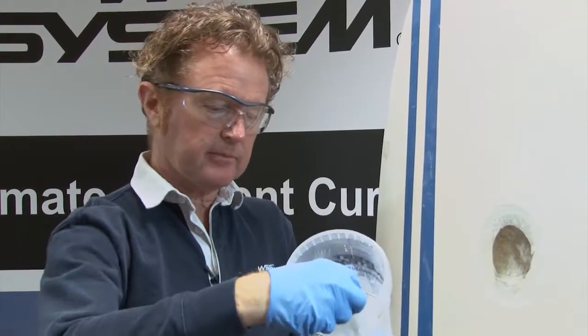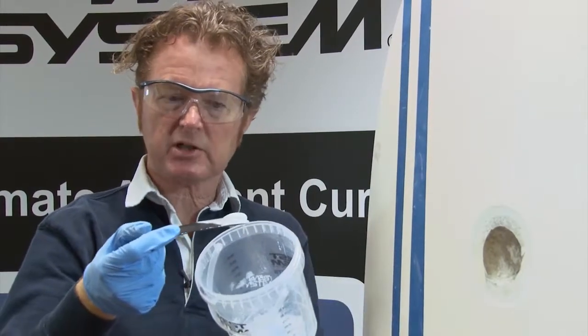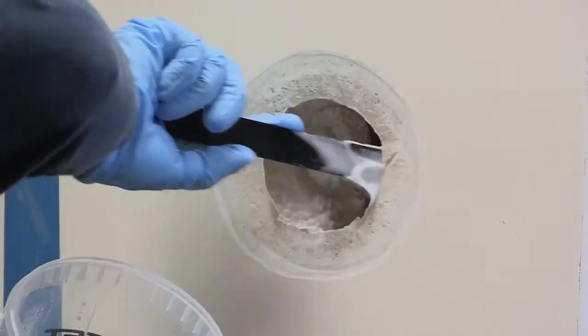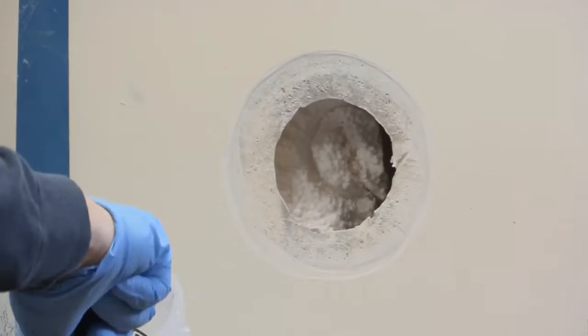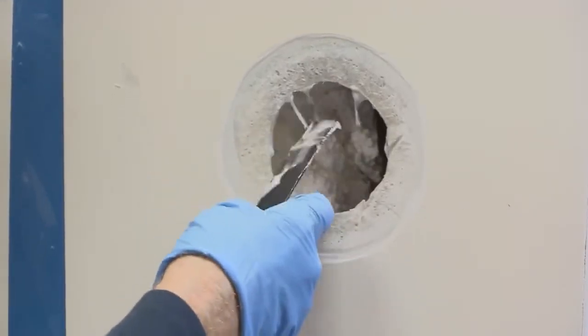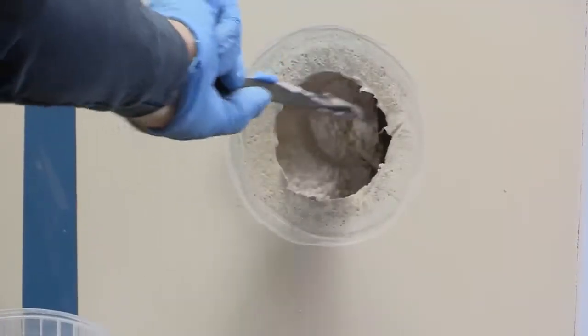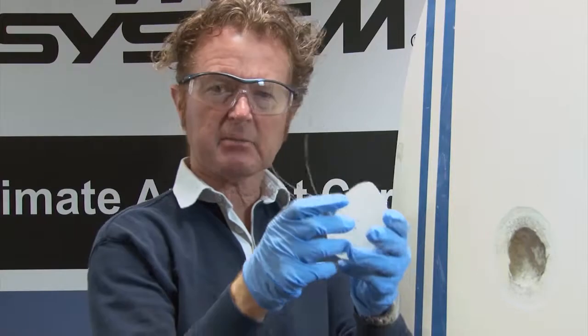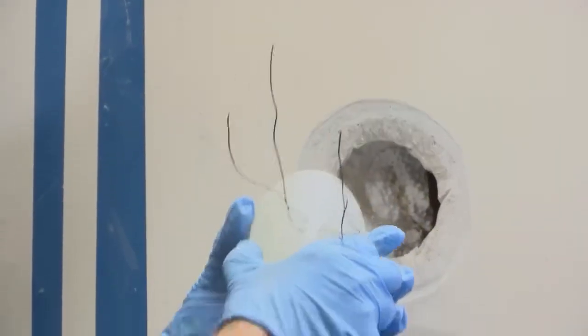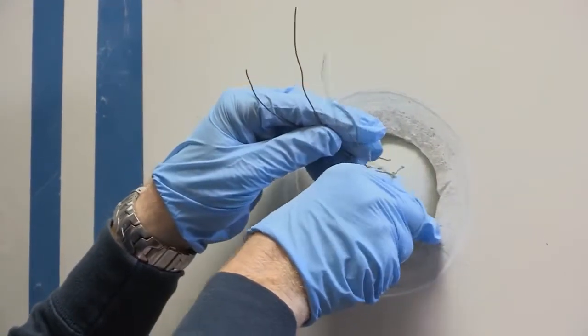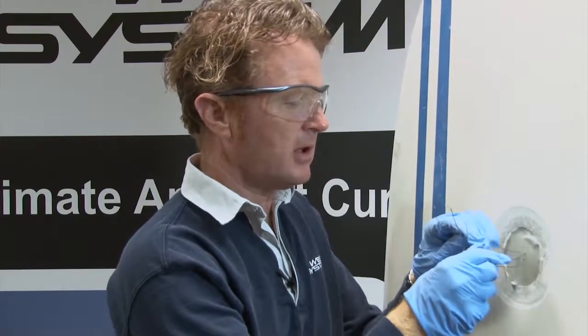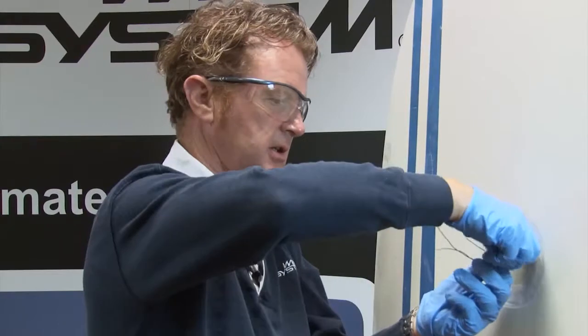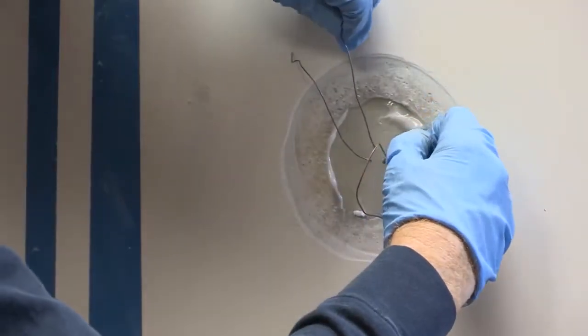Very important. To bond our backing plate in place, we're going to use a thickened mix of epoxy. I've used West System 406 colloidal silica and West System epoxy mix. And I'm going to just do that just by dragging a thin bead back around the edge of my repair. Keep a nice clean bit of work. Just ensuring I've got a nice bead just at the back face. I then take my backing piece with all the wire pieces, bend it so it will pass through the hole, and then secure it back on itself like this. You can use the wires to secure the plate in place.